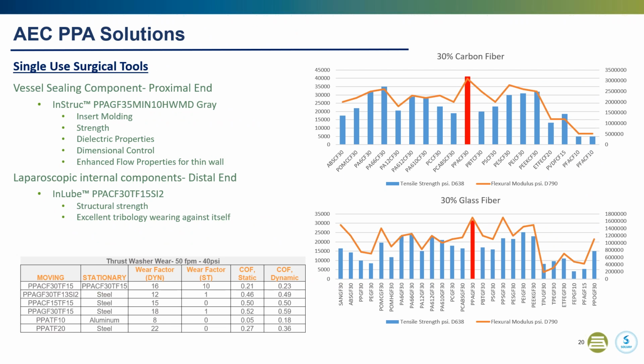Locked in, custom colored. Another application on the other end of the instrument would be our InLube PPA, 30% carbon fiber, 15% Teflon, 2% silicone. If we go up to the chart, 30% carbon fiber, you can see how it towers on flex and tensile as well. Your 30% carbon fiber PPA, you're looking at a flex modulus around 3 million, and your tensile strength towers there at about 41,000. Great structural strength. Usually for the components in the hand of the surgeon, you have plastic on plastic wearing. So it's great that it's stiff, but we also need some lubrication protection.